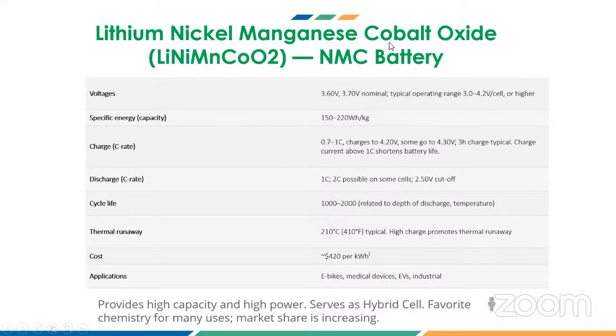But here we use cobalt oxide, therefore the charging cannot be done very fast. Only 0.7 to 1C is possible, because we use cobalt oxide. But the discharge rate is increased when compared to cobalt oxide. 2C is possible. Already I told you, high discharge rate is important for grade climbing or hill climbing, as well as sudden acceleration. The cycle life also increased, but still it has one problem: thermal runaway. If the temperature exceeds 210 degrees centigrade, it could explode.